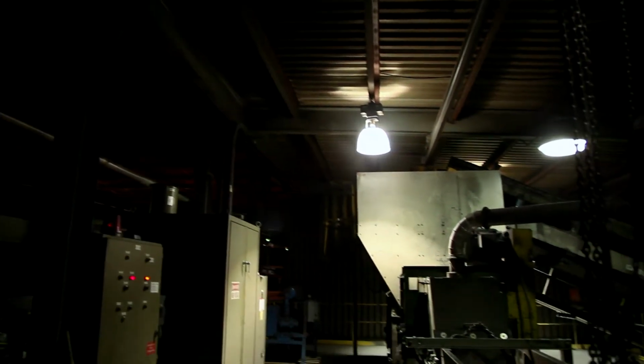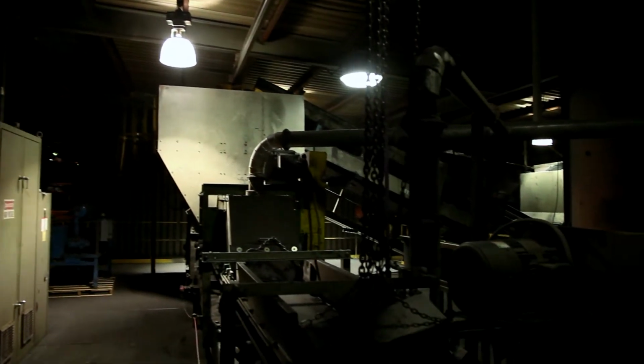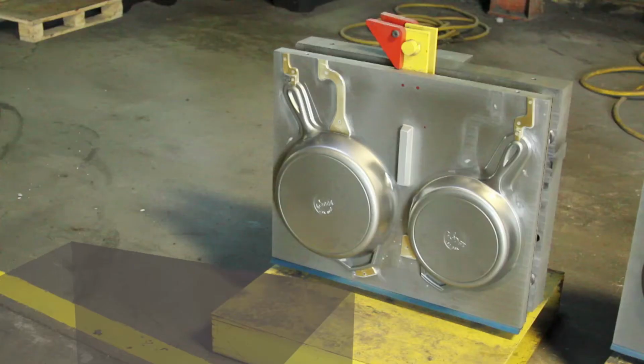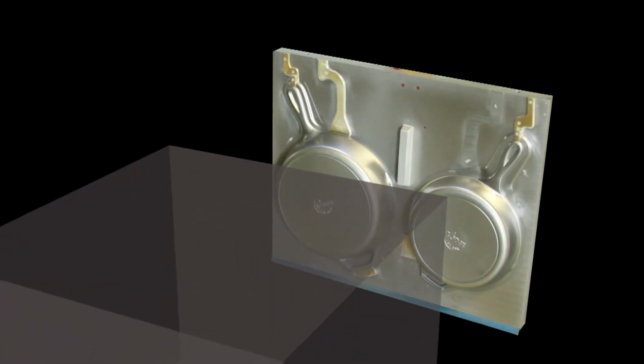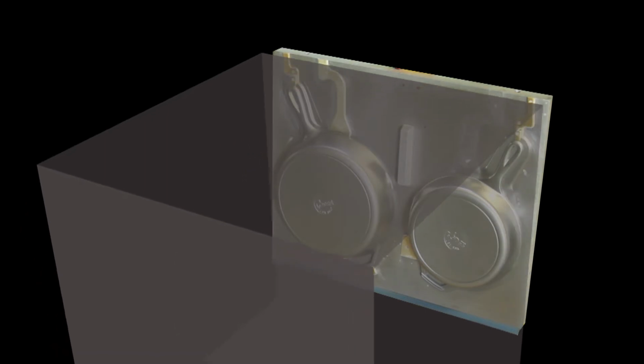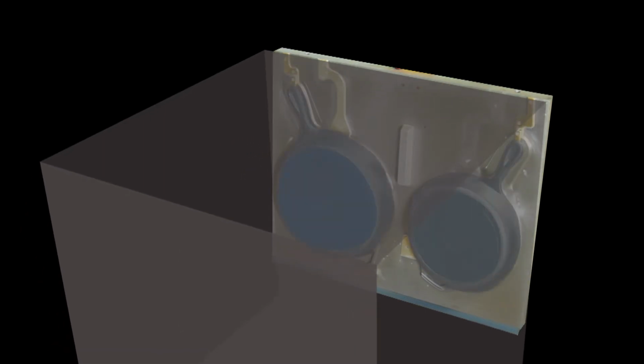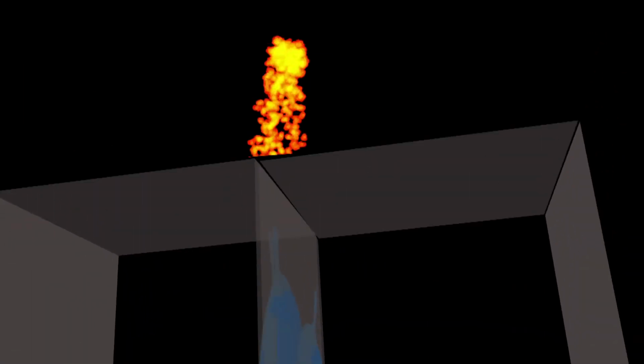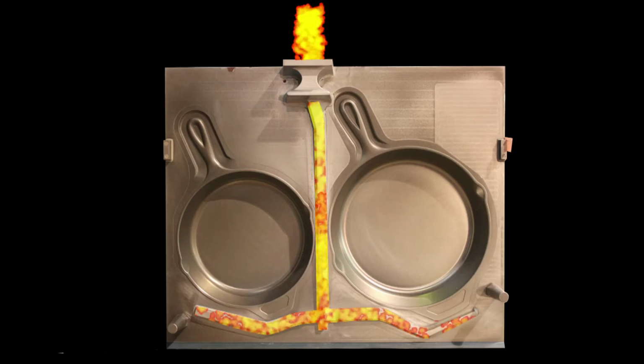Lodge uses sand molds, an ancient technology. Sand molding remains the best and most practical way to cast iron. Our molten iron is so hot it would melt almost any other material, but the sand can hold its own against the heat. This is how it works. Compressed air forces moist sand into a pattern that is squeezed at 700 to 1,000 pounds per square inch to form the exact contour of our skillet. Exact reverse impressions of both sides of the pan are formed in the cavity in the sand. Molten iron fills the cavity, creating your skillet.